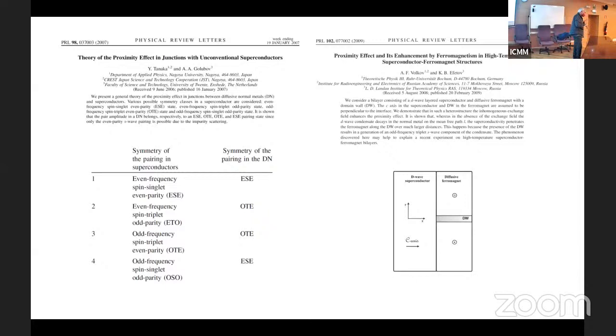We haven't measured it. I think there may be other possibilities. You can reach an isotropic pairing state with D wave pairing if the pairing is chiral, a complex dx squared minus y squared plus i dxy. This would also give you a rather isotropic pairing, which would allow for the long range, but certainly it has to be demonstrated whether there is this chiral superconductivity or not in the system.